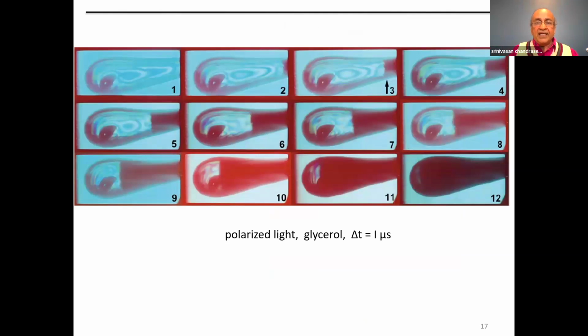showing that even as the crack is propagating, the stresses in the glass revealed by the fringes, the stress field, doesn't get perturbed at all till the crack has almost reached a point. So at any point, the fringes stay the same till the crack front actually comes very close to the fringe, and only then you see a distortion in the stress field. And again, you can see some fingering events ahead of the main crack.